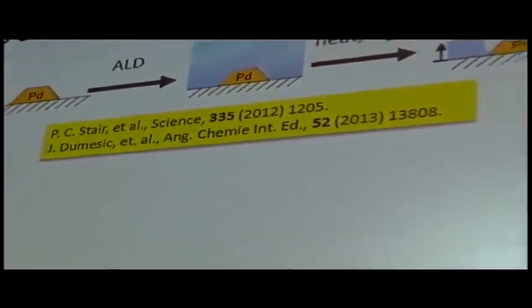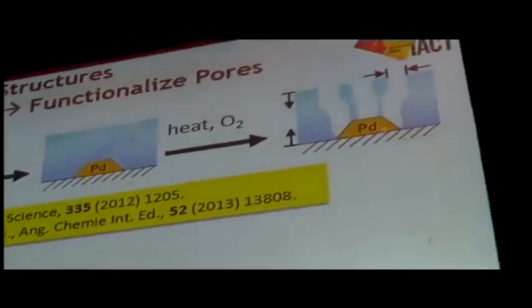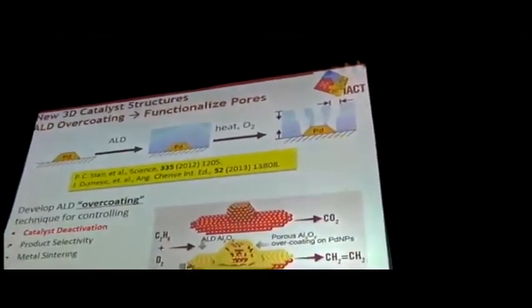As I said, what we've discovered is that ALD overcoating can help a lot in both the selectivity and the stability of these catalysts. We actually kind of stumbled across this. I'll be honest with you, we were looking to see when we put aluminum over the top of metals, when would we lose communication with that metal. And we found that out and published on that. But what we didn't expect is that if we calcine these materials at high temperatures, we would generate new pores down to the surface of the catalyst, which would still allow the metal to be active. Peter Stair was the one who first discovered this.